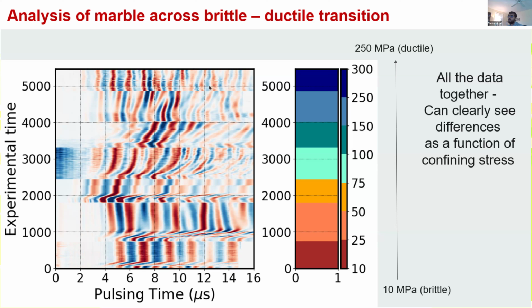If you look at how the structure of the waveform is changing during the experiments, again, these are the same type of experiments. You have confining pressure, you have constant strain rate, so you build up differential stress. The structure of these waveforms, you can see at the bottom, the experiments at 10 MPa, there are some sharp changes that occur as you do the experiment. If you look right at the top, which is going to be our ductile regime, we don't see those sharp shifts in the active source data, especially in the coda, during the process of the experiment. So that starts to give some hint that there may be information in here about the rheological state of the sample just by looking at the active source data.